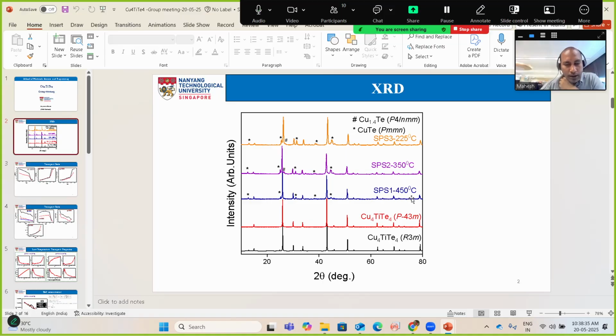Oh, okay, the initial powder. I mean, you are able to get the good phase only at high temperature SPS. You don't want to go beyond 550 degrees centigrade because of decomposition. You are unable to make a good phase with the low temperature SPS.